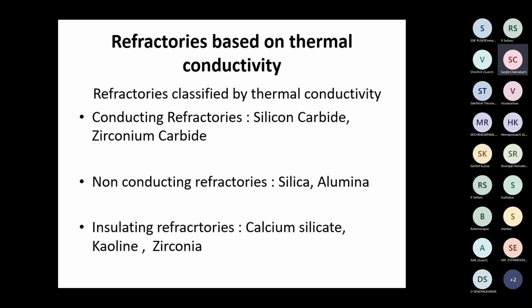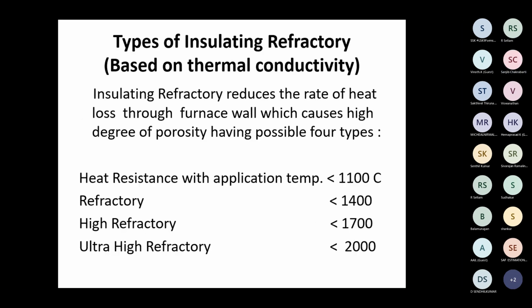Refractoriness is based on thermal conductivity. The refractory is classified by thermal conductivity. Conducting refractories, silicon carbide and zirconium carbide, are highly conductive. Non-conducting refractories are silica and alumina. Insulating refractories are calcium silicate, kaolin, zirconia. In insulating refractory the porosity is very high. Insulating refractory has to have quite good porosity, otherwise it will conduct.